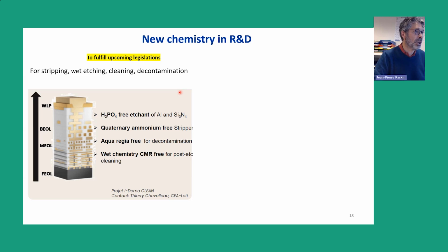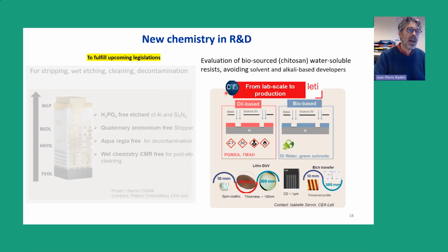We can find several European projects that are trying to replace, to substitute, some of the chemicals for stripping, for wet etching, cleaning, and decontamination. We can mention here, for example, the evaluation of biosource water-soluble resist for avoiding solvent and alkali-based developers. For example, at CEA-Leti, in collaboration with ST Microelectronics, they try to introduce chitosan biosource resist for the back end of line, and they start to have some successful research for that.